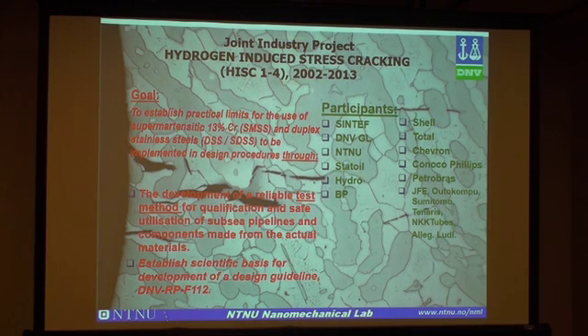In the beginning of this millennium, several major accidents happened in Norway for the offshore pipelines due to hydrogen-induced stress cracking. The scale of these accidents was so huge that the industry wanted to start the investigation immediately. So we started several testing projects, HISC-1, HISC-2, 3, 4, over the last 11 years, from 2002 to 2013. The aim of the project was to establish practical limits for the use of super martensitic and duplex stainless steels, to be implemented in design procedure through testing.